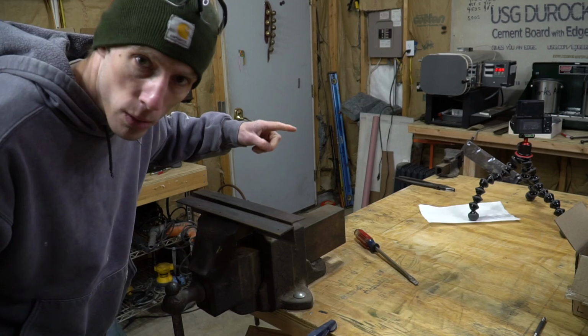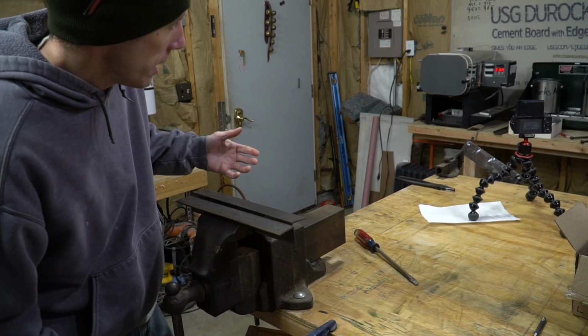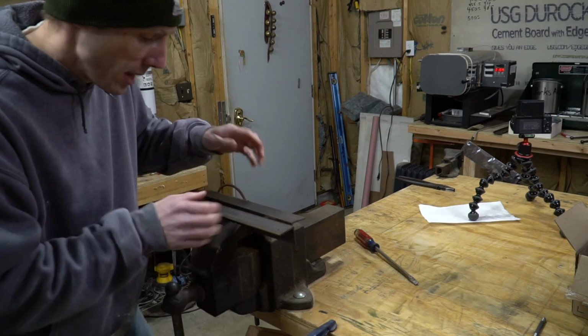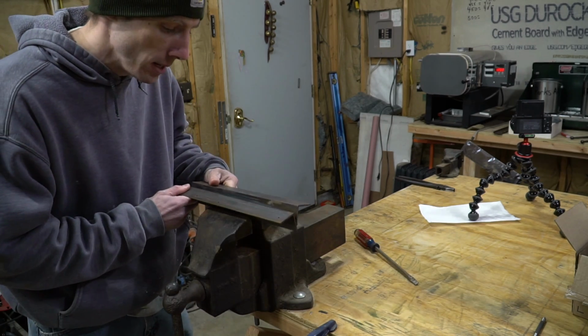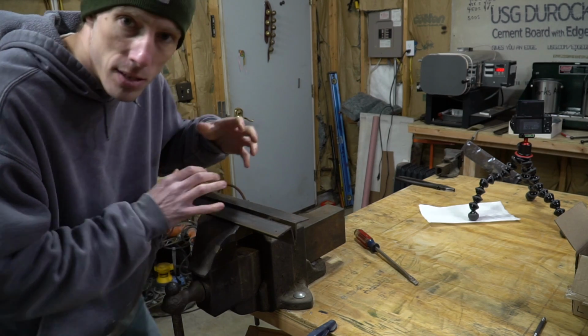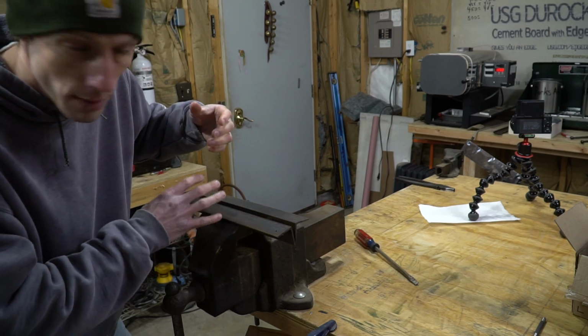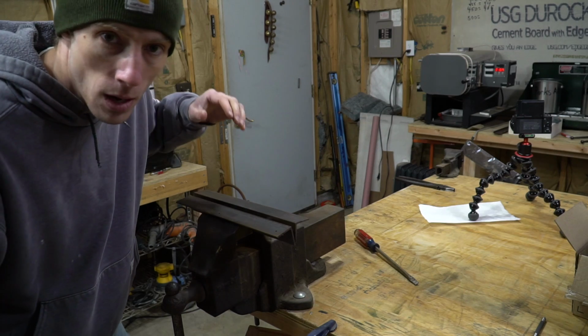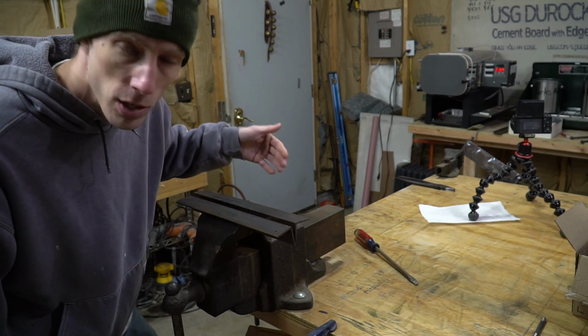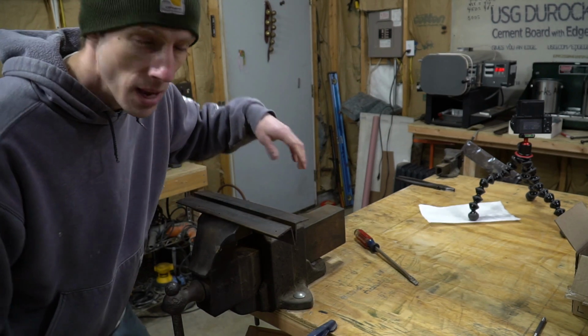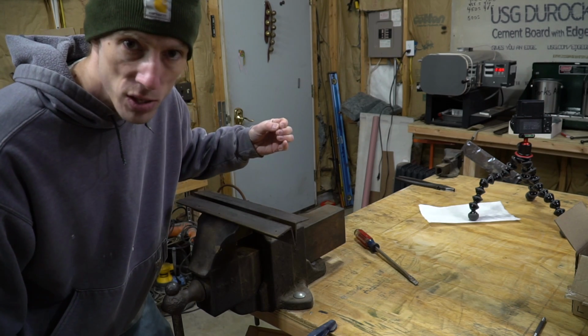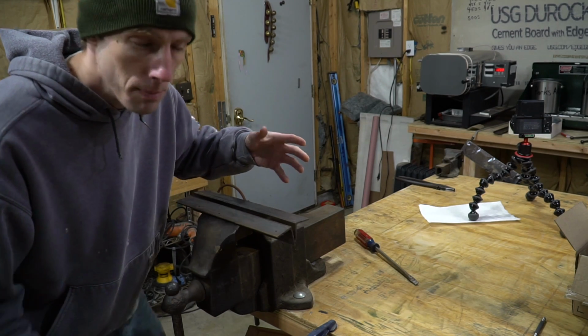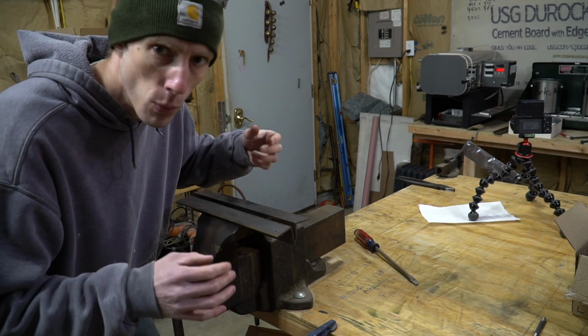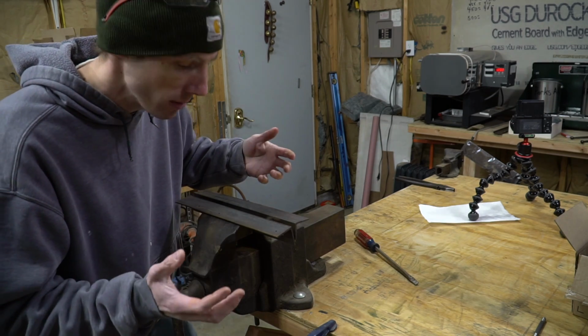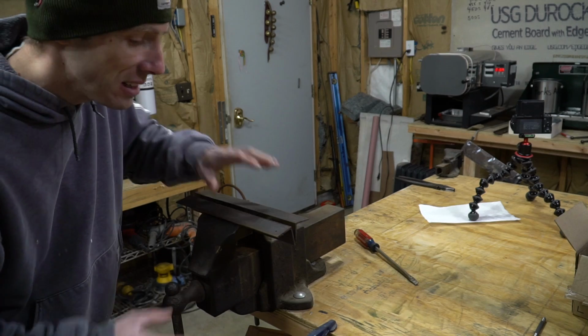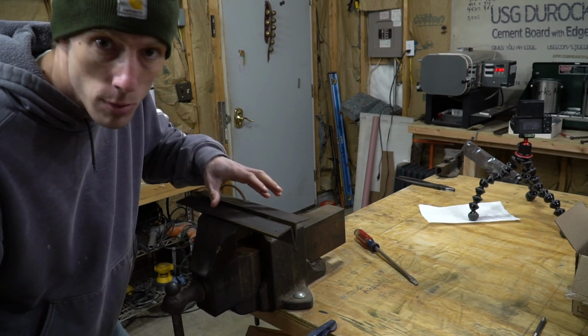Our blade is almost cool enough that we can handle it and unwrap it and get it back into the oven. What I'm doing now with these two pieces of angle iron is getting them set up in the vise, and these are going to be our blade straightening devices. Basically, we're going to bring the blade up to austenizing temperature, 1475. We're going to quench it, and then we are going to pull it out of the quenching oil. And while the blade is still hot, between the temperature ranges of about 400 degrees and 200 degrees, we're going to get it over here and clamp it real tightly between these two pieces of angle iron.